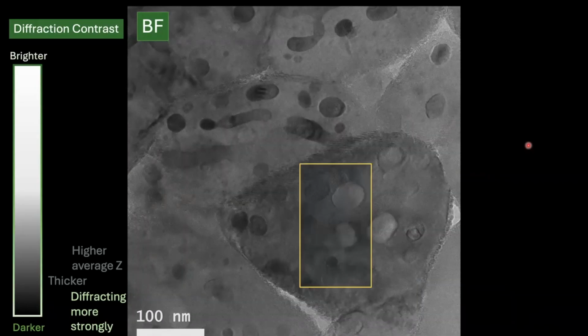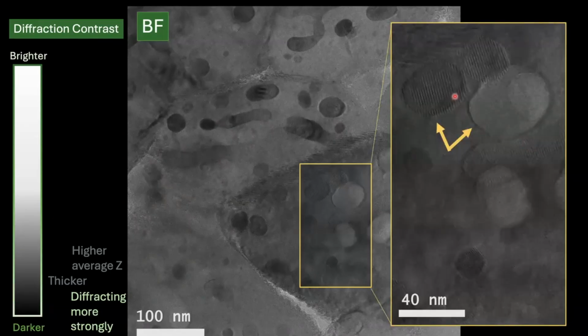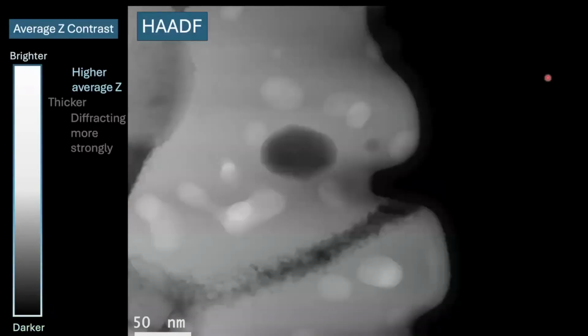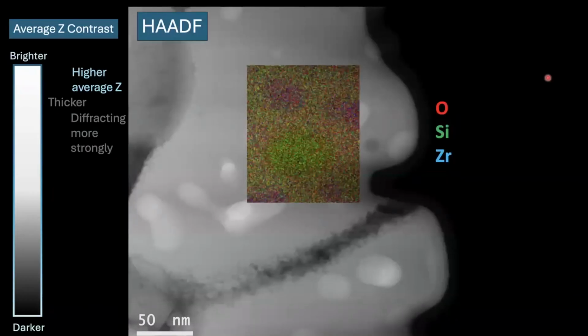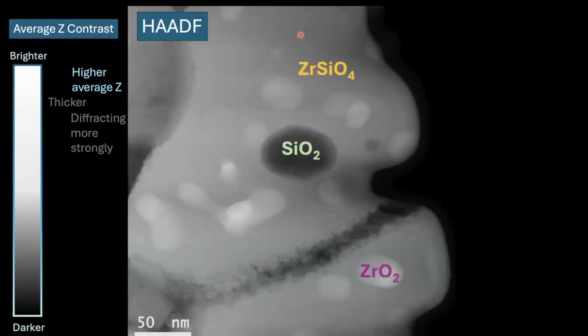Then if we zoom in more, we see that there are some crystalline inclusions. You can see that by the interference fringes, and there are some amorphous inclusions. So we went to HADF and said, okay, let's do STEM, let's do EDX compositional mapping, and figure out what this stuff is. So we did oxygen, silicon, and zirconium, and we determined that most of this is zirconium silicate, likely zircon. I did do some diffraction pattern indexing, but I didn't include it in this talk.